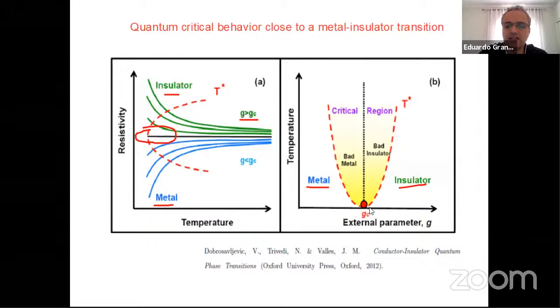But then when you have this critical behavior, you have a phase transition between this metal and insulator phase. And this phase transition happens exactly at T equals 0. And that defines what you call a quantum phase transition. And it turns out when we have a quantum phase transition, there is some critical region where you have very strange behavior, and it's believed that even the superconductivity in the high-Tc superconductors may be somehow related with this strange behavior where interesting physics arise.